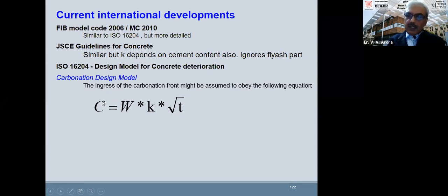And when it reaches the cover concrete, it depassivates the reinforcement. When the carbon dioxide enters, it consumes the calcium hydroxide available, and the pH value of the concrete comes down. A lower pH then breaks the passive layer around the reinforcement, and reinforcement starts corroding from that time onwards. And once the corrosion comes, the cracking and spalling occurs.